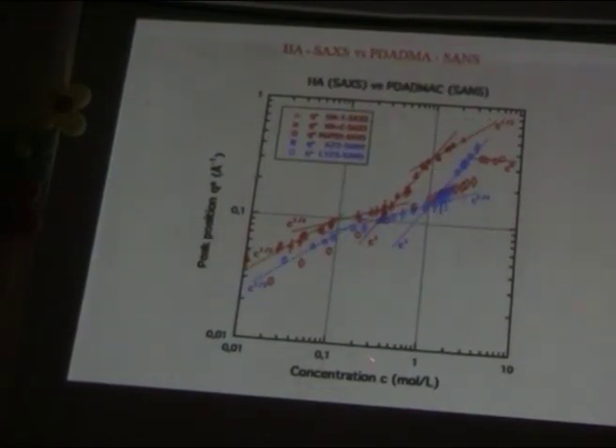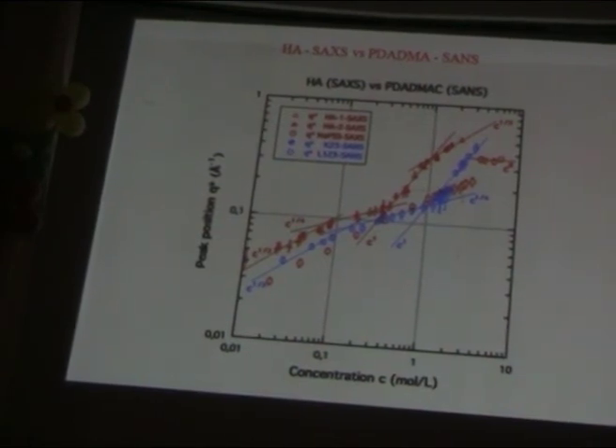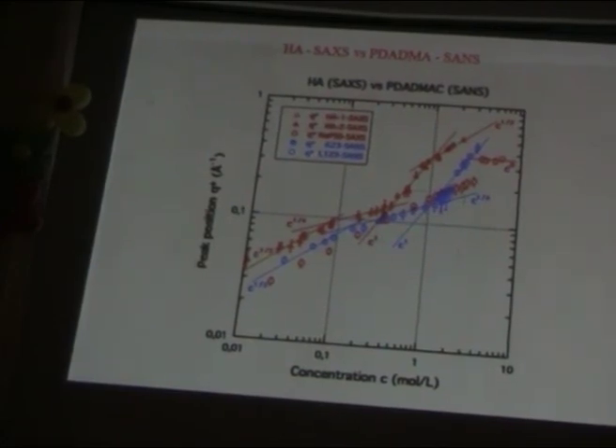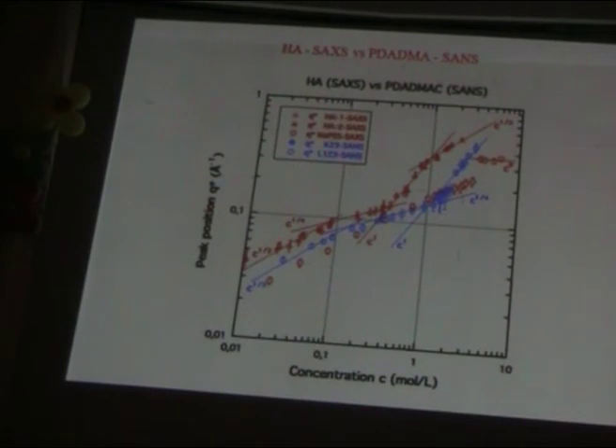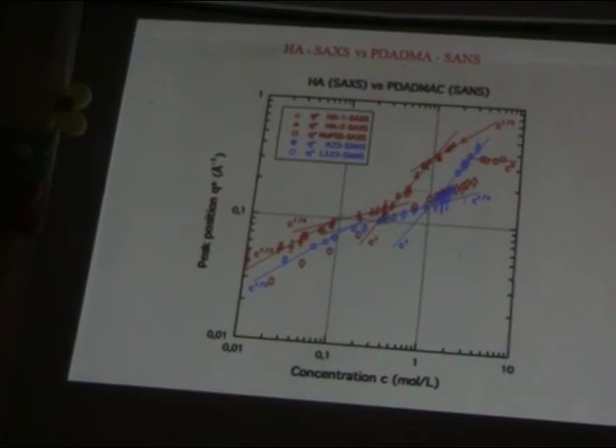I will stop here. You see, with the hyaluronan, there are no condensed counterions. In this case, if you use X-ray, you see only the macroion, because the counterions are in the solvent. You can compare that with the PDADMAC, but in that case you have to use neutrons to observe only the macroion. Okay?